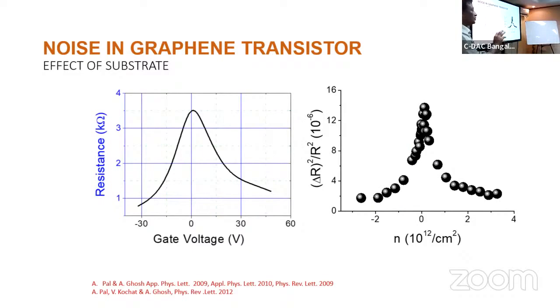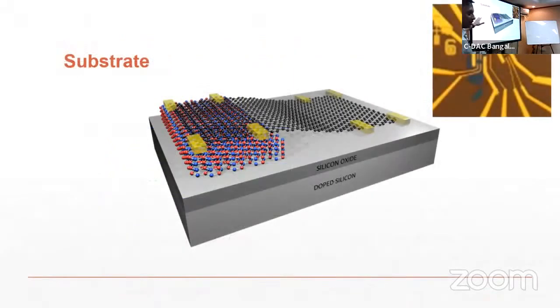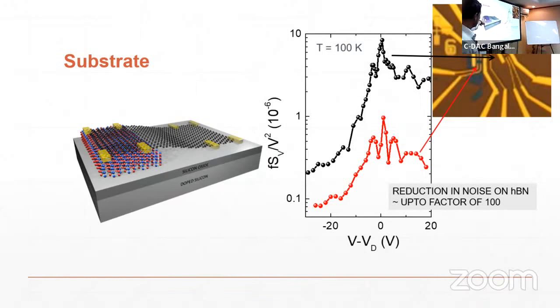What we did after that, we wanted to reduce this noise. And we found something really interesting. We found that if you take graphene and put it on a single crystal environment, this is what I was telling you a few minutes ago, instead of silicon oxide, which is an oxide, if I insert a layer of single crystal boron nitride, which is also a two-dimensional material, you essentially get a region. Now we measure the noise from both sides, from the part which is on single crystal boron nitride and the part which is sitting on oxide. You can see the noise from the oxide is 100 times larger than the part of the same sample which is sitting on boron nitride, which is a single crystal.